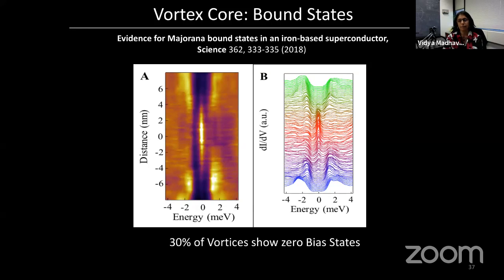One thing I must mention that I'm not going to dwell on is that we always get bound states inside a vortex core. And those bound states, we've known this for a long time. These are just the normal Caroli-de Gennes-Matricon bound states. The point about those bound states is that there is no reason for them to be at zero bias. However, depending upon the position of the Fermi energy with respect to the bottom of the band, the spacing between these normal, regular Caroli-de Gennes-Matricon states could be so small, so clustered together, that it seems as though they're right at zero bias in a particle-hole symmetric fashion.